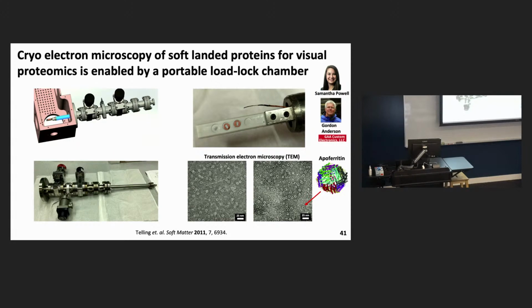So we were interested in whether we could just purify a protein complex and put it on a surface, and what would it look like in the TEM if we soft landed it? So we did that for apoferritin, which is shown on the right. These are two results from two different samples. You can see, yes, indeed, we can produce fairly high densities of these proteins. The objective in cryo-TEM is basically to cover the surface in a single layer of these things so that you can sample all possible orientations, then do a 3D reconstruction. So what you don't want is things preferentially oriented one way or clumped up on top of each other. So we think that this is a promising result and something that we're hoping to build on in the future.